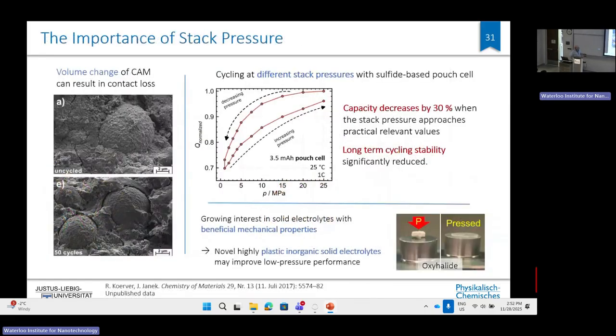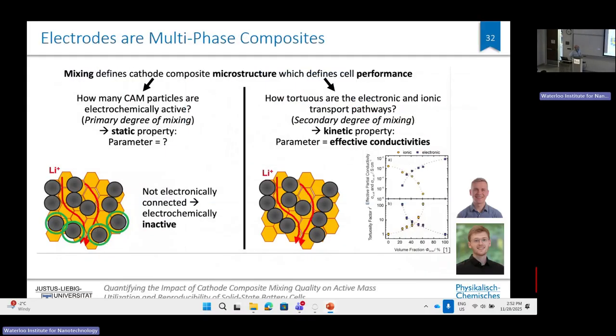I made a comment here. I think what is really interesting, and Linda is at the front end of that research, is that there are materials meanwhile, particularly oxyhalides, that are really viscoplastic. They can easily deform, and I would say again, for the interface design in cathodes, clever materials design is also needed. Polymers may enter into that, but polymers have their disadvantages. At these high potentials of cathodes, they are often easily oxidized and are not so stable. So that's why an inorganic solution might, again, be better at this point. There also, Linda really looks into that in depth.